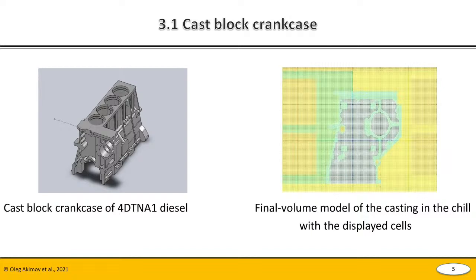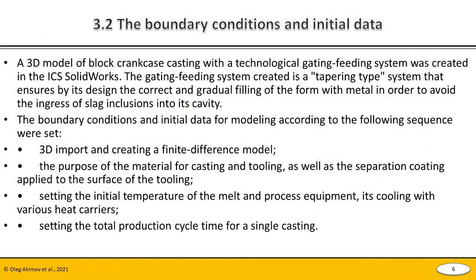On this slide, we can see 3D models of the cast crankcase of the diesel, the final volume model of casting in the chill with the displayed cells. Slide, please. The boundary conditions and initial data. 3D models of the block crankcase casting technological gating-feeding system were created in the ICS SolidWorks. The gating-feeding system created is a tapering system that ensures by its design the correct and gradual filling of the form with metal in order to avoid the ingress of slag inclusions into the cavity.